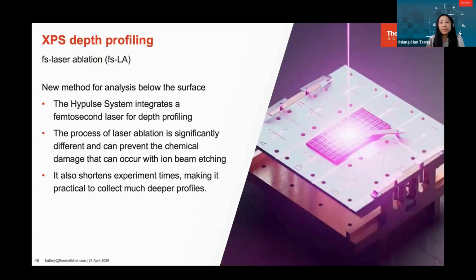It's a very nice improvement when we switch to cluster ion profiling. But we still need to remember it doesn't work for all materials. In particular, over the years, it has been shown that the cluster sources don't work that well for a certain number of inorganic materials. Because of this, we tried to find a solution, so we recently introduced a new method for depth profiling, using a femtosecond laser as a source to do the material removal.